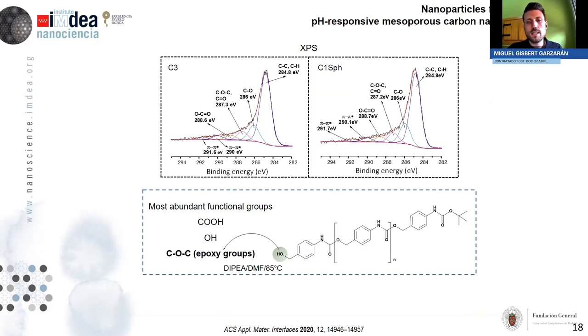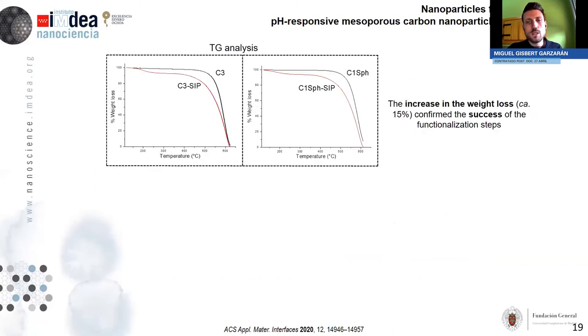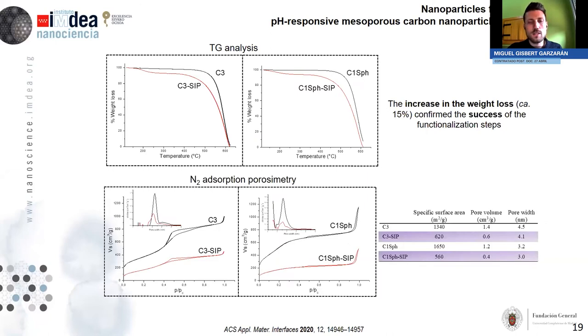Okay, so we analyzed these carbon nanoparticles with XPS to check what functional groups we had on the surface. And we concluded that the most abundant functional groups were the epoxy groups. So we took advantage of that to add the self-immolative polymer and functionalize the nanoparticles. So again, we characterized the nanoparticles. We can see here an increase in the weight loss after the functionalization steps, a reduction in the textural properties after the functionalization steps, which is indicative of the presence of something that is covering the surface.